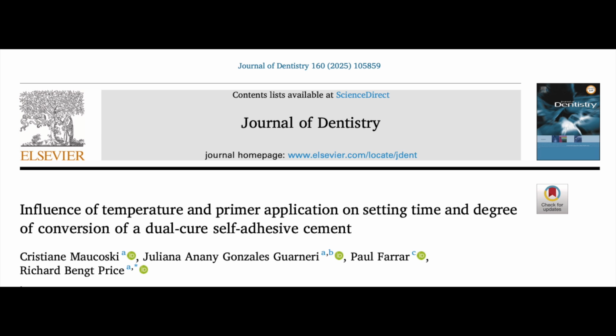So I think there's a really critical point emerging here, especially for researchers listening. Which is? That doing these lab studies only at room temperature, 23 degrees C, might not give us the full picture. Definitely not. It probably doesn't accurately reflect how these cements behave inside the mouth at, say, 32 degrees or 37 degrees C, clinically relevant temperatures. Yeah, this study really highlights that. Future research arguably needs to incorporate these higher, more realistic temperatures. It's a crucial point for translating lab findings to clinical reality. You need to test under the conditions where the material will actually be used.